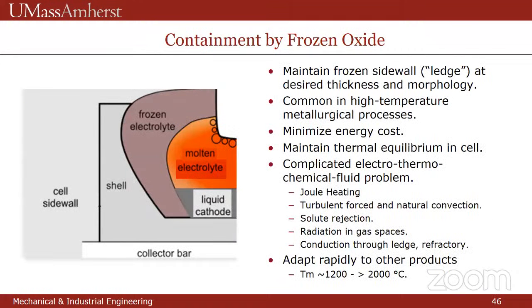And so one common way is to have a frozen ledge of electrolyte. This is used with the fluorides in the aluminum cells. And so you want to maintain a frozen ledge that's the desired thickness and morphology, so that it contains the electrolyte where it's in thermal equilibrium, and the metal where the frozen ledge is so different chemically that they have limited interaction. And you want to do all of this while minimizing the energy cost and maintaining robust equilibrium, so that when you have an excursion in the cell, you don't lose the ledge, because usually then you lose the furnace.